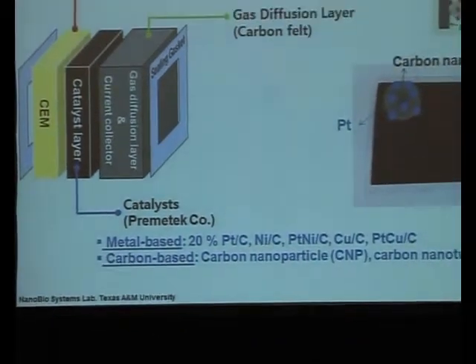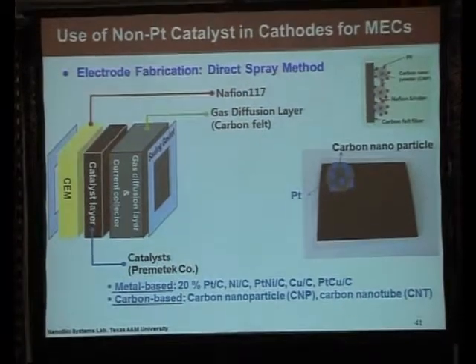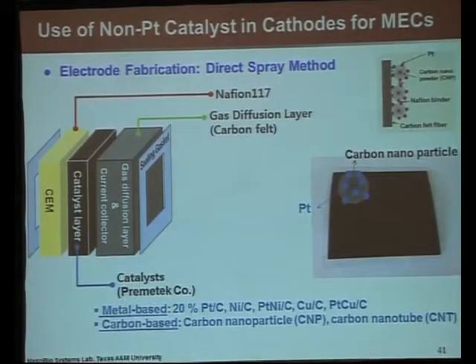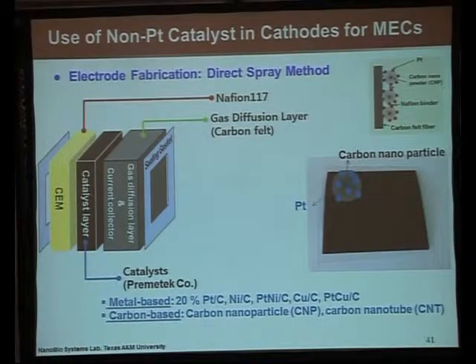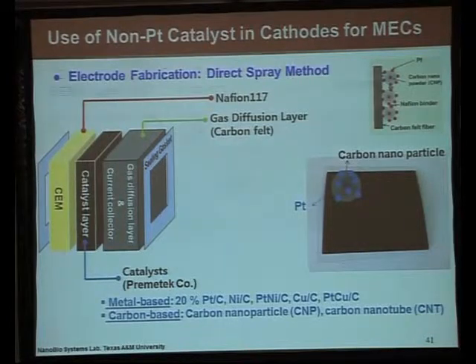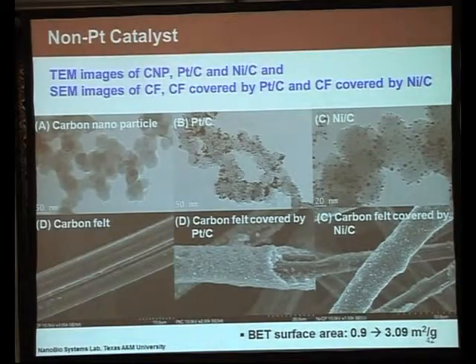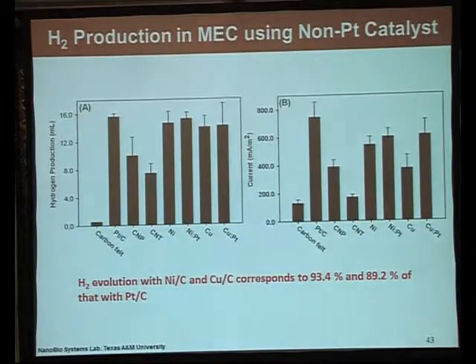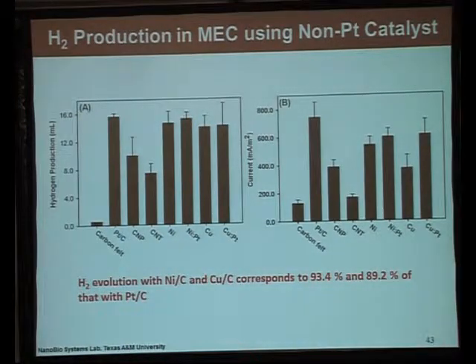On the capital side, we have also started to look into non-platinum catalysts because the use of platinum is probably one of the biggest costs in microbial fuel cell. So we have tried different metal-based product and carbon-based product. What you're seeing here is the direct adhesion of these different nanomaterials on these electrodes. And what you're seeing here is, in this case, we have been using it in the system in a MEC for hydrogen production. What you can see here is that these hydrogen evolution using a nickel or copper has a very high efficiency, very close to platinum in terms of the hydrogen evolution. So this is a very promising result for us that there is a potential of using a non-platinum catalyst.